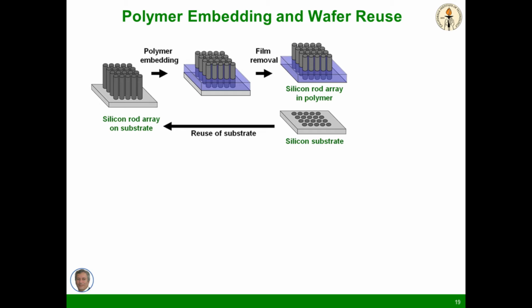In addition, we end up, after we peel it, with the stubs of silicon in the microwire array that then we dissolve in a quick etch in base and then put it back into the toaster oven after putting more catalyst down and then repeat the process. So this is like making money in a template when you take that expensive substrate and use it over and over again. And the metal we have subsequently replaced from gold with nickel, or even better, with copper. And we can plate that by an electroplating process, just like making a printed circuit board. And so we have a full cycle that allows us to make these micro rod arrays in a piece of plastic.